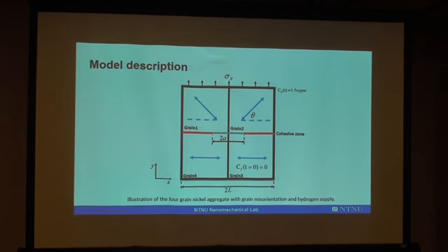In this way, we keep the lower grains fixed, and we rotate the upper grains about the out-of-plane axis in a symmetrical manner. We can thus parameterize the misorientation angle theta in the range of 0 to 90 degrees. To investigate the grain size effect, we further parameterize the grain size L in the range of 1 to 50 micrometers.